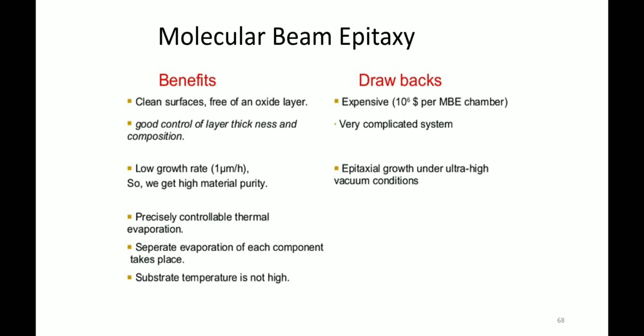Then the epitaxial growth has to be carried out under ultra high vacuum condition. The problem with ultra high vacuum is that most of the time, if there is a small leakage, then you will not be able to get the ultra high vacuum. So you have to maintain the system so that every time it reaches that ultra high vacuum condition. So you have to maintain the greasing and the gaskets. Okay, so you have to degas the system after the deposition has been carried out. So there are so many things to be maintained so that every time you are able to reach the ultra high vacuum. Okay, so this is not an easy task, to maintain the ultra high vacuum every time. Okay, so this is all about the molecular beam epitaxy technique.